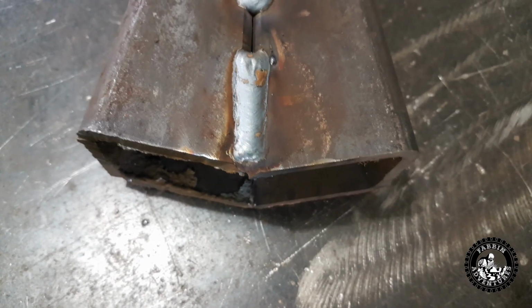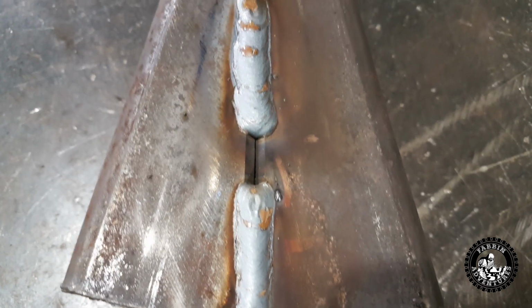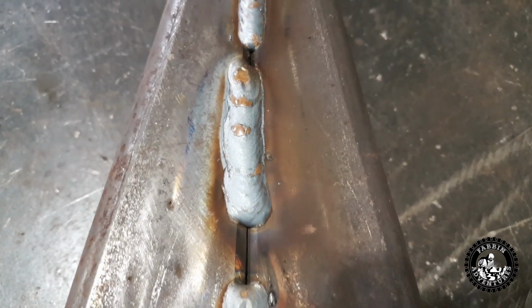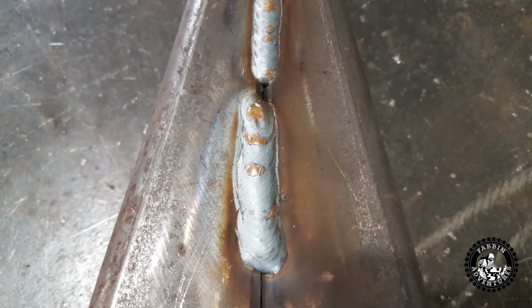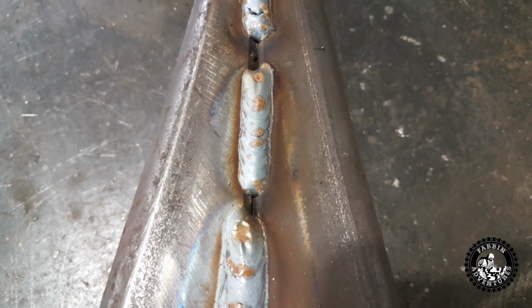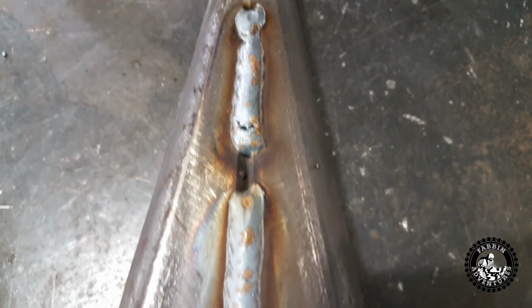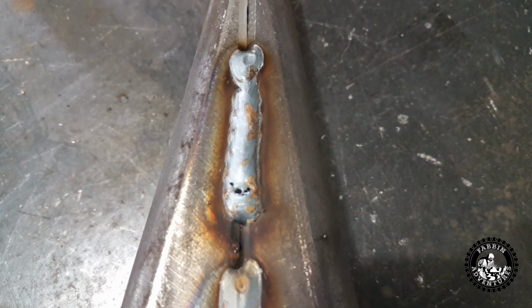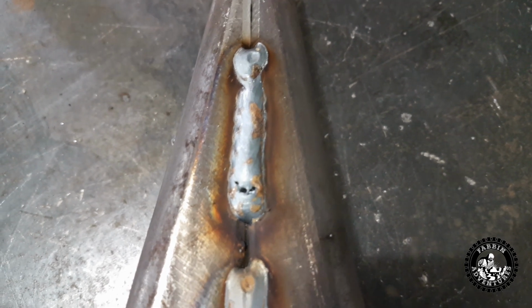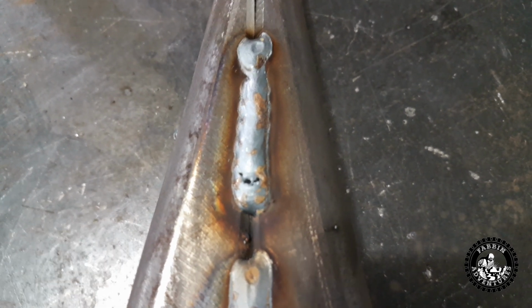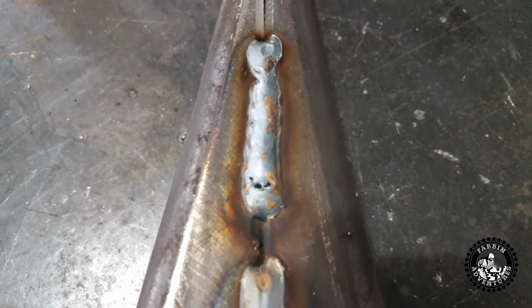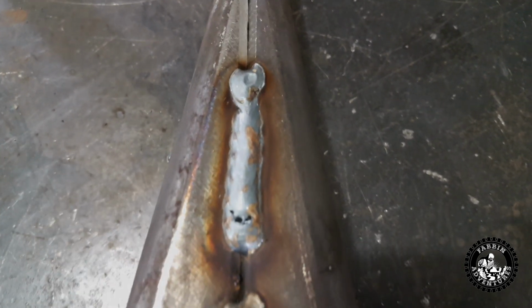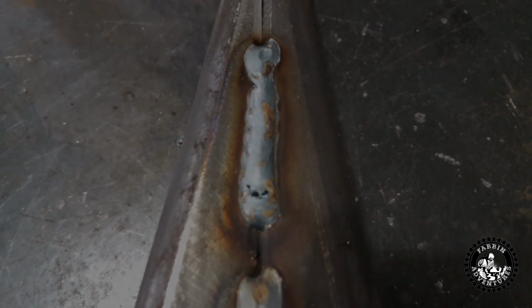So okay, you can see the zigzag of mine, and you can see Crystal's zigzag. She went a little too wide out of the crack, and her wire was going way beyond the crack. And then here's my modified zigzag, and then here's Crystal's zigzag, and you see the porosity there, the holes in the weld. She must have been holding the gun too far away, and we weren't getting the shielding gas on it, and oxygen was getting to the weld, and it created some porosity. There could have been some contamination in there too. But otherwise, decent welds.